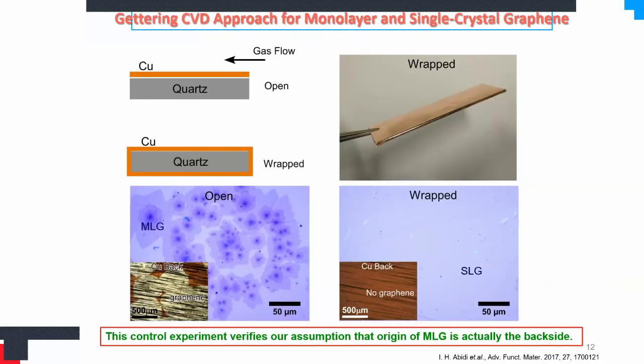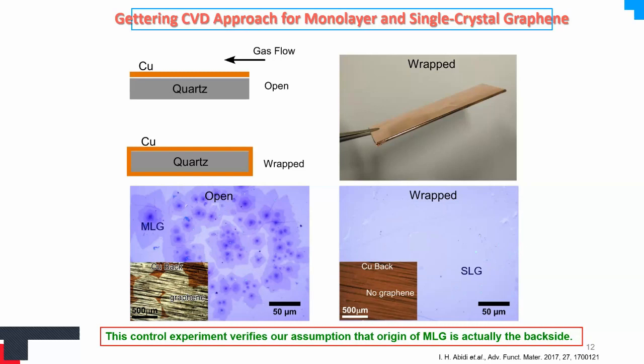However, I did a very controlled experiment to see whether only the top surface matters in the CVD growth, or the bottom surface of the copper foil also matters. I did a very controlled experiment in which I have two different configurations. In the first one, I did what we usually do during graphene growth: we put the copper foil on a quartz substrate and put it inside this CVD furnace. In the other one, I wrapped the copper foil so that only the top surface is coming into play during the reaction, and the backside of the copper foil is not coming into the reactions.